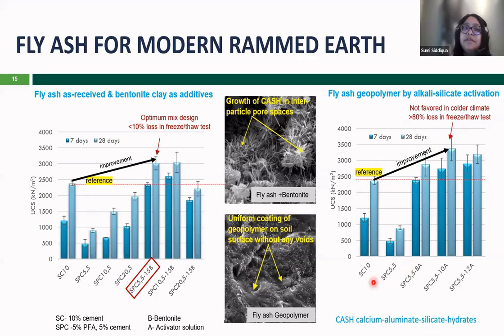So this is very interesting, because when you are using the geopolymer alkalization, it improved the strength. And we have been looking into different data from literature that alkalization, the geopolymer process, geopolymerization is important to improve the strength. But then if you look into the freeze-thaw data for this material, we see that we lose more than 80% of the strength over the period of time.